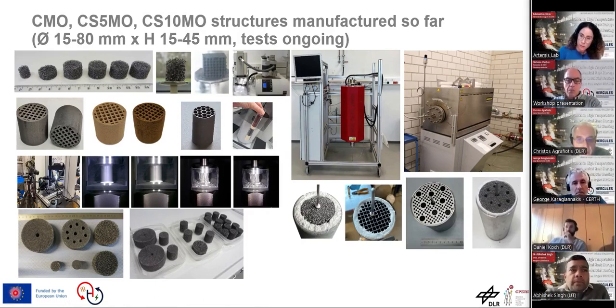Here we see all these kinds of structures that we synthesized and shaped in this project, tailored, let's say, to the various diagnostic instruments. We shape very tiny mini foams and honeycombs on the top left that can go on a TGA. We shape 1 inch honeycombs and foams of different cross-section that are good for diagnostic instruments and laboratory furnaces like the red ones you see there, and also mechanical tests as you see below, crushing strength tests. And we shape also larger dimensions of honeycombs and foams which are suited for testing rigs, like the furnace you see on the right-hand side, which has a bigger diameter tube and can accommodate specimens of higher diameter as you see below for thermochemical tests.